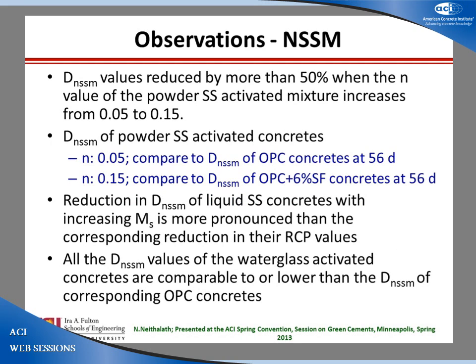With non-steady state migration, again, the results are now much more in line with what you expect. You don't see a dramatic drop for one type of concrete, but the reduction with liquid activated, or solution activated, sodium silicate increases with the silica modulus or silica content more than the reduction in RCP values, and we'll talk more about that when we do the microstructure. So all the values are comparable to or lower than the non-steady state migration values of corresponding OPC concretes, which gives you an indication that yes, you can make them with durability levels comparable to or better than OPC concretes.